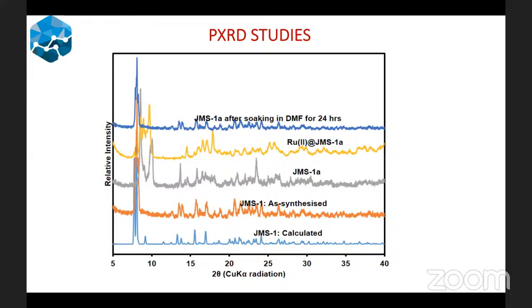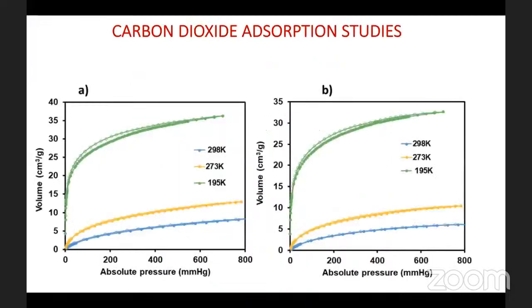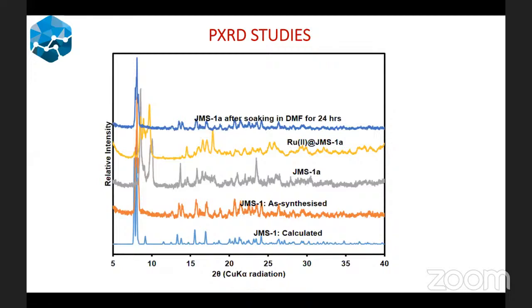Now, we also looked at how the structure would change after insertion of this bulky molecular complex inside our MOF. These are the PXRD studies that were done on the MOF. As you can see, we have the calculated pattern, which was simulated from the single crystal X-ray data. And of course, we also have the as-synthesized material, which clearly matches the calculated pattern, confirming phase purity of the synthesized material. Upon activation, JMS1A, the activated material, still retained some of the peaks present in your as-synthesized material.